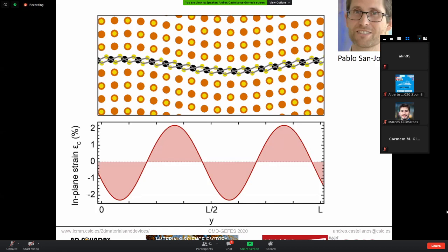Not really. It's similar to the example of the backplane-induced rippling, right? So remember the elastic substrate. You place the crystal on it, you release the strain, and then you get these ripples, and the ripples are tensile and compressive. It's similar to that. But in that case, you are only applying the strain at the bottom of the layer, not at the top, right?